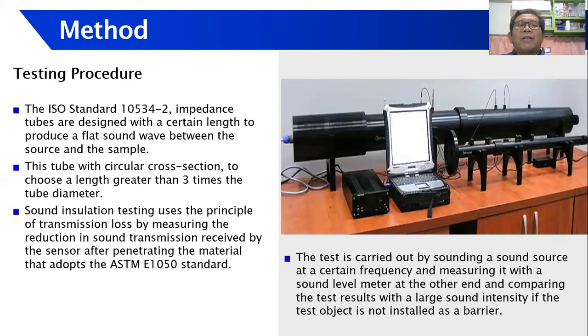Sound insulation testing uses the principle of transmission loss by measuring the reduction in sound transmission received by the sensor after penetrating the material, which adopts the ASTM E1050 standard. The testing is carried out by generating a sound source at a certain frequency and measuring it with a sound level meter at the other end, comparing the test result with the sound intensity if the test object is not installed as a barrier.